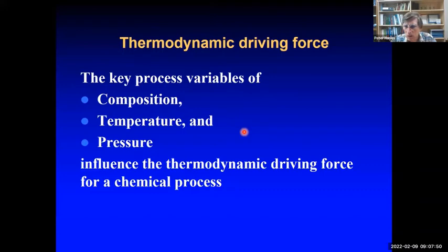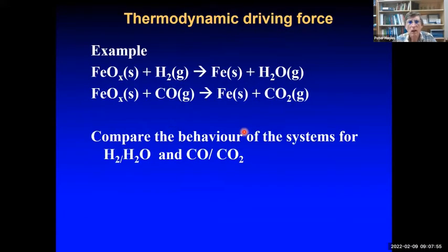And I want to show you a couple of examples of how we can look at that and take away some learnings from it. I'll start with a very simple system, the iron oxide system. And here we're trying to remove the oxygen from the association with the iron. There are two principal ways in which we can do that in industrial practice. We're using hydrogen or CO gas as the reactant gas to pick up the oxygen and change it to H2O or CO2. So I want to just, from a thermodynamic perspective, compare the behavior of those two systems and how those process variables can change the thermodynamic driving force for the reaction.